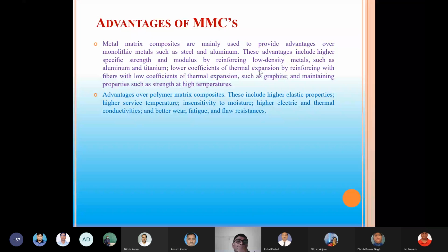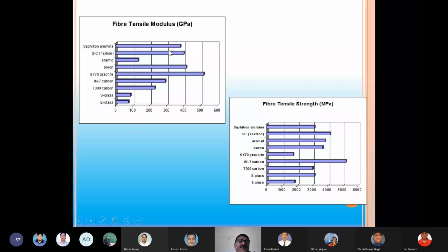If we talk about the advantages, these composites are mainly used to provide advantages over the monolithic metals, and also over polymer matrix composites. This includes higher elastic properties, high service temperature, insensitivity to moisture, high electric and thermal conductivities, and better wear resistance. If you see here, this is the fiber tensile modulus for different materials, it may be alumina, silicon carbide, aramid or boron. In the case of graphite, you will find it is more. And if you see the fibers of different silicon carbide or boron, you will find accordingly the strengths are better.